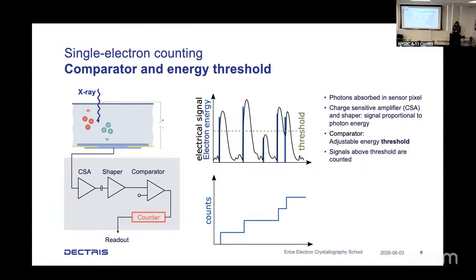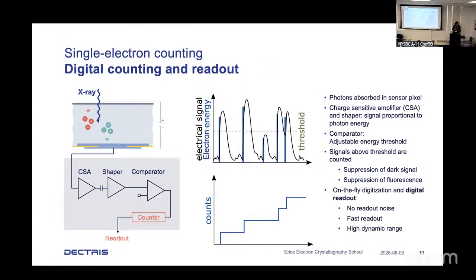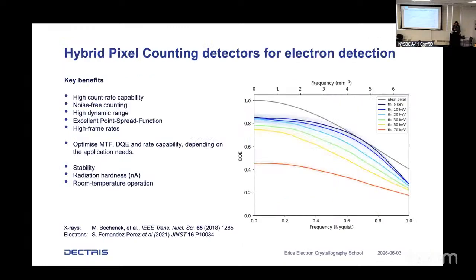So each pixel is a small detector on its own, and we can adjust the threshold, and we can use this to suppress the dark signal or also the fluorescence in case of X-rays. And because the counter is in the pixel, we read out digital signals. So there's no readout noise because it's a digital signal. It can be fast readout, and it can be designed to have a high dynamic range.